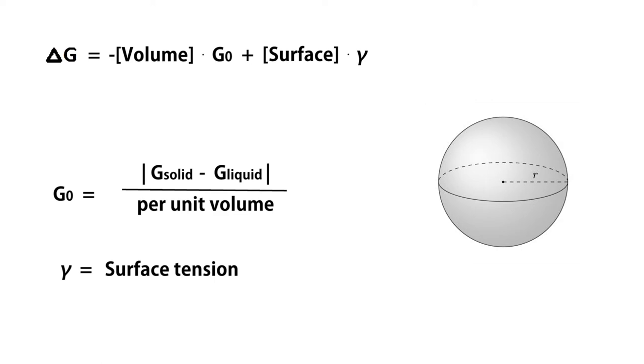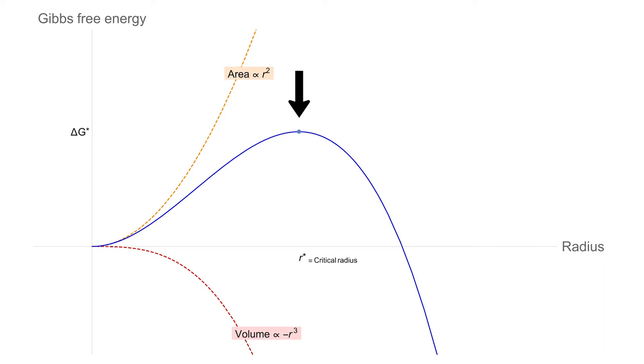If we take the case the ice forms in a sphere we can then write the change in Gibbs free energy as delta G equals minus four thirds times pi times r to the third times G zero plus four pi r square gamma. If we look in the picture of the radius of the ice sphere formed plotted against the difference of the Gibbs free energy we see that after the radius of the sphere has become bigger than some critical radius here, the Gibbs free energy will only lower the bigger the sphere becomes and with that the more ice is formed. For radii lower than a critical radius forming of ice doesn't give any Gibbs free energy lowering for the water.